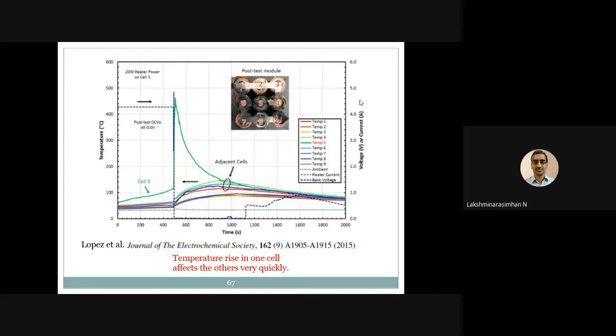And these are all detrimental to the entire battery. So the polymer membrane, the polypropylene membrane, which is separating between this, will melt at around 120 or 130 degrees. That's all. Short circuiting happens and immediately it will trigger. So that's the main problem.